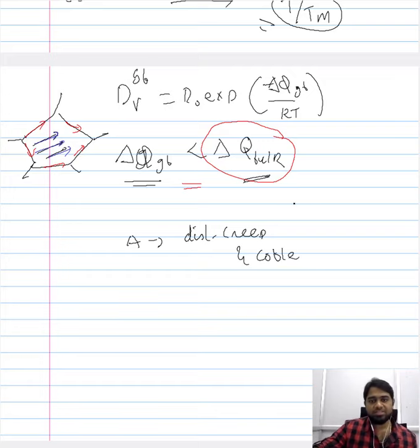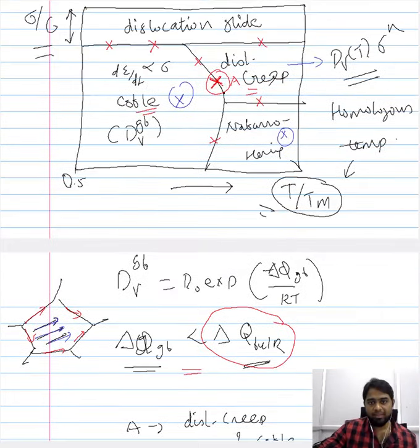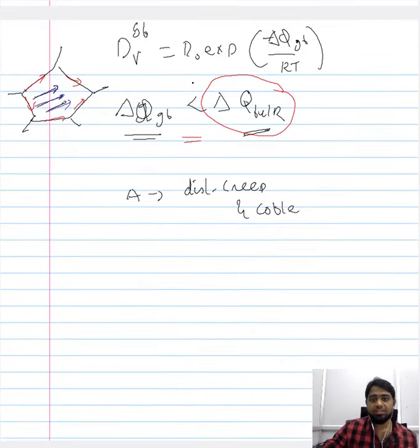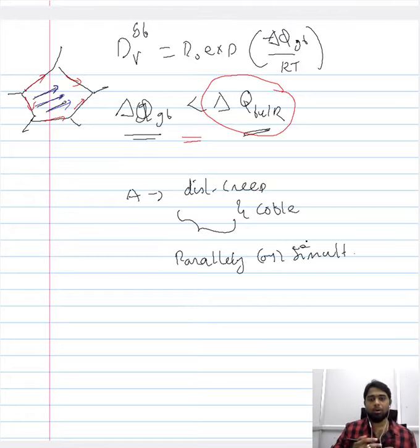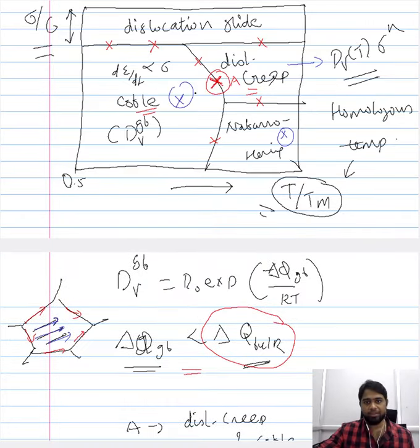What it means is that when you have a point that lies on the line that separates two creep mechanisms, these two creep mechanisms are operating parallelly, or simultaneously. So the line that separates two different mechanisms indicates that the two mechanisms being separated are operating together.